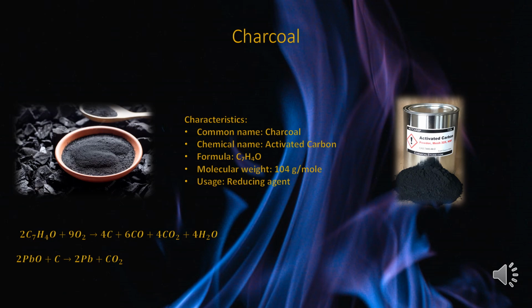It is for this reason it can be said that the charcoal will have a molecular weight of 12.0 grams per mole versus the 104 grams per mole as shown. It is said to be the strongest reducing agent available, but due to cost, flour has become the substitute. During fusion, it has been shown that charcoal will react with any available oxygen, resulting in the two gases and water vapor. The remaining elemental carbon will react with the litharge, reducing it to elemental lead.